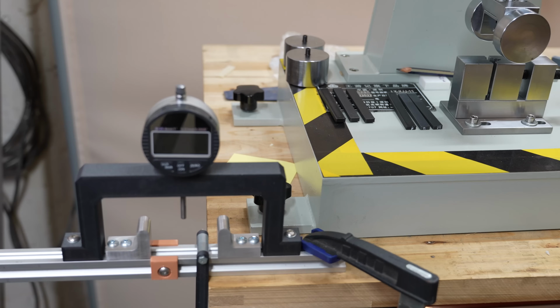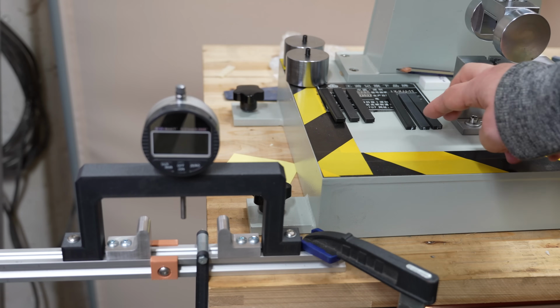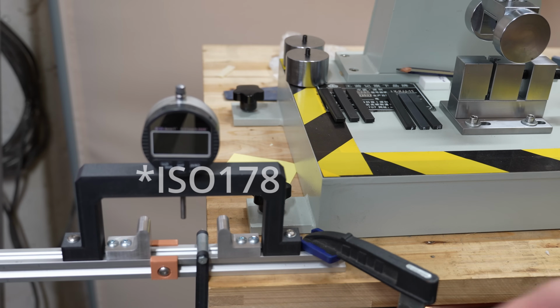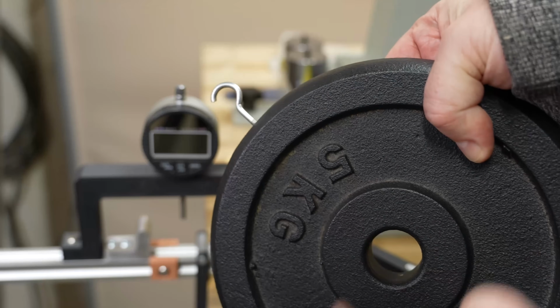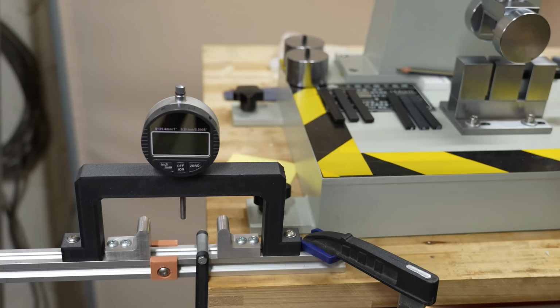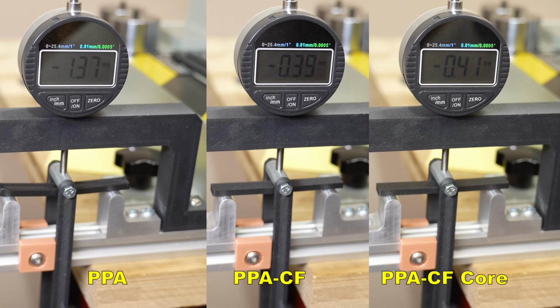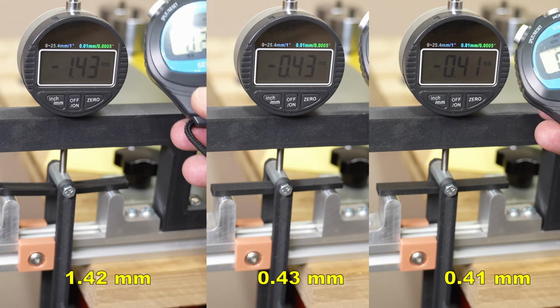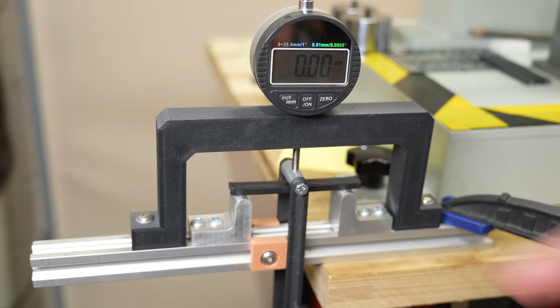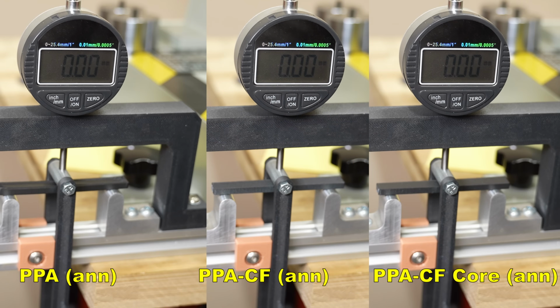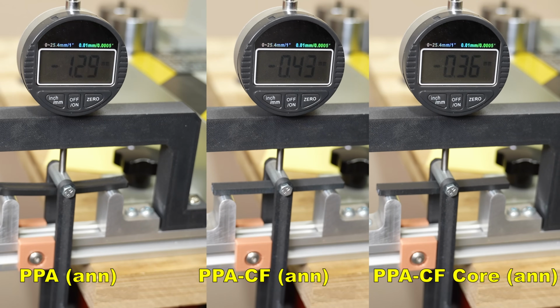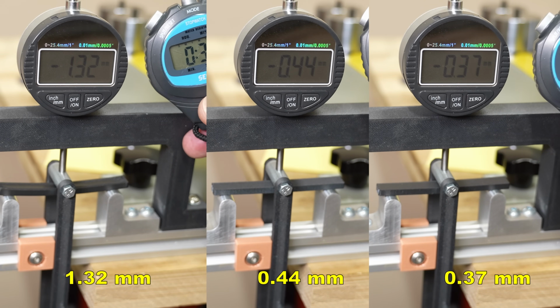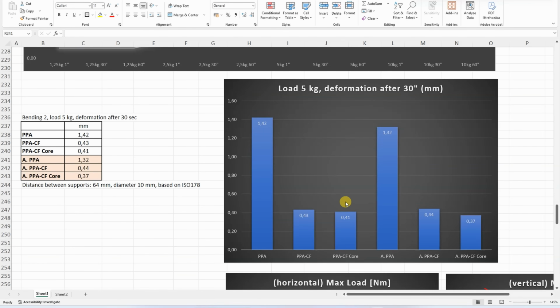Another 3-point bending test, and here I have regular and annealed versions, and this is a little bit different because this follows better that ISO 178 standard with the bigger distance and with this radius. And I will just place a 5 kg load and I will follow the deformation after exactly 30 seconds. Non-annealed versions, I am placing the load. And this is after 30 seconds. PPA annealed, which already has some deformation. And again placing the load, initial deformation. And after exactly 30 seconds. Carbon fibers really help here, but the effect of the annealing is not significant.